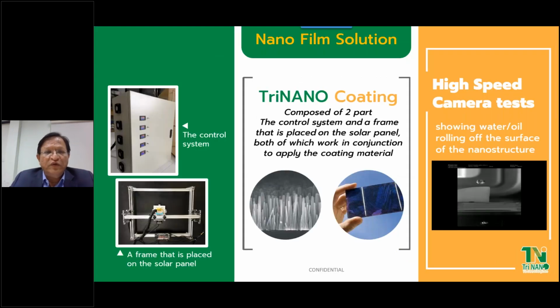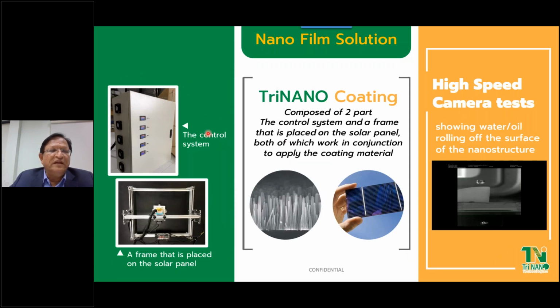So how do we do the coating? You can see on my screen on the left side, there is a control panel. This control panel actually controls the viscosity, the flow rate, the thickness, the current, the voltage, the temperature, all these process parameters and the coating thickness parameters. And there is a frame which sits on the panel, and this center part moves along the X and Y direction on the solar panel. When it moves, by virtue of the electric current, you'll get a microstructure something like this, which is a very dense bamboo tree forest-like structure. So when the light falls on it, it doesn't get reflected, it gets trapped.